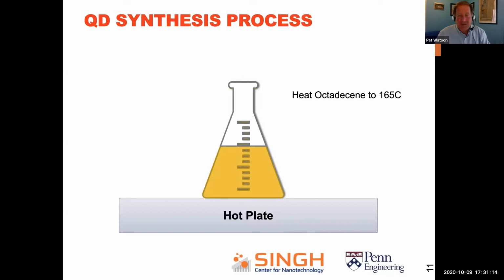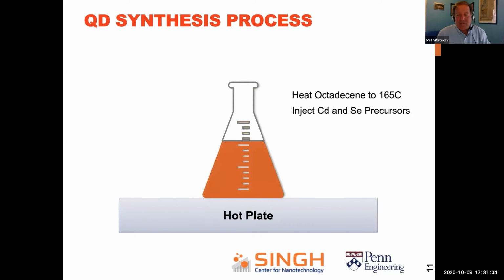So here's a cartoon of the process. We use this in our laboratory course in ESC 536 to demonstrate quantum dots and to use them potentially for device applications. So we start with a hot plate. We have a little Erlenmeyer flask. We put in this octadecene, our solvent. We heat it up to 165 Celsius, and then we inject our precursors, and we have the cadmium and selenium already in solution. We inject just a little bit, and almost instantly you see the solution start turning orange, because we start absorbing photons, the light in the blue region. And this is characteristic of all kinds of quantum dots, not just direct band gap ones.